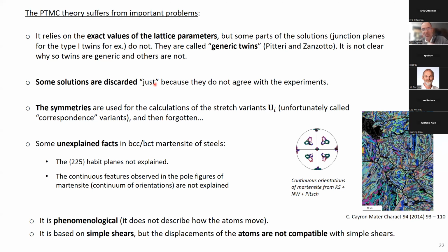So you have to solve some equations, and at the end you say, I keep this solution because it's in agreement with experiments, and this solution I discard because it does not fit with experiments. It's not very satisfying. Another thing is that the symmetries are treated quite strangely. They are used to calculate the stretch variants, sometimes unfortunately called correspondence variants, and then they are completely forgotten. So we do not understand the rules of the symmetry. There are also some unexplained facts.